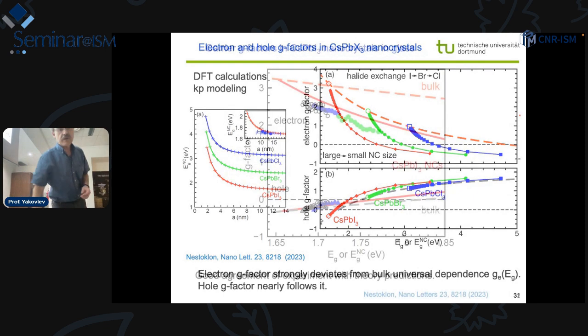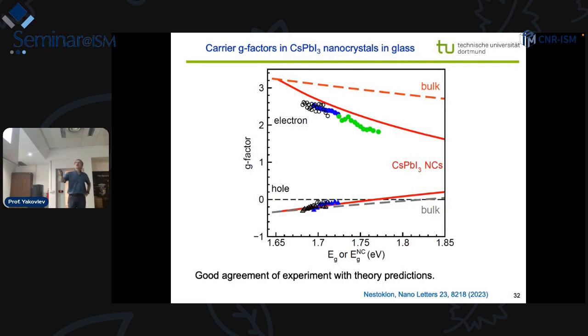We checked this experimentally on cesium lead iodide nanocrystals in glass. For the large nanocrystals, we observed that these predictions work very well. The electron g factor changes much faster than in the bulk, and the hole g factor stays nearly constant. We also have data, which I won't show today, that the hole g factor starts to deviate from the theory predictions under strong confinement, and we still need to understand what additional states need to be mixed. So measuring the g factors gives rich information for band structure theory and calculations, and I hope it can help to refine these parameters.